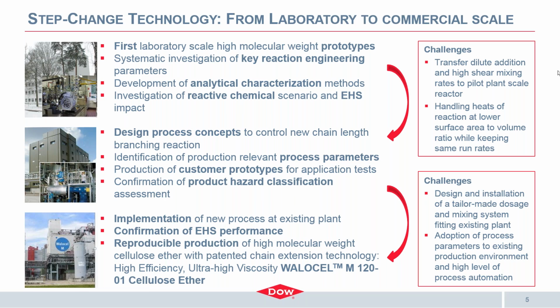And with lab scale material, we developed new characterization methods for these branched cellulose ethers that didn't exist beforehand. For pilot plant scale, we had to adjust mixing and dosage regimes and ensure that this exothermic reaction was fully under control. For this, we confirmed sufficient heat of reaction transfer with a small volume to cooling mantle ratio of the pilot plant reactor that we had at the time. And in the pilot plant itself, we evaluated process concepts and finally confirmed the process parameter settings, and at the same time were able to produce material for evaluation at our customers that we collaborated with.